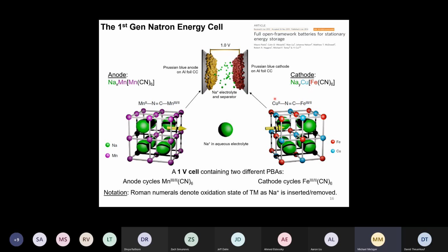So in this material, as we already said, we have copper, which is coordinated with the nitrogen. We have the hexacyanoferrate framework structure, and iron coordinated to the carbon. So that's this iron. And in the way that Natron cycles the cell, iron is changing its oxidation state between 2+ and 3+ as we insert and remove sodium from the cell.